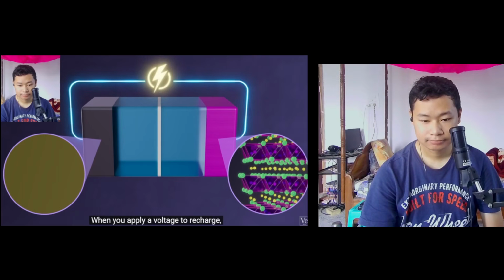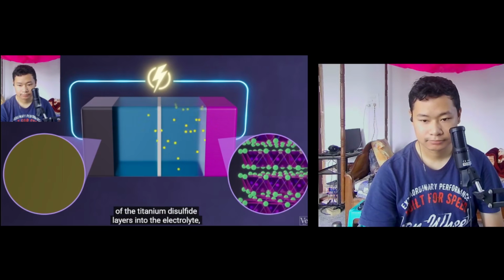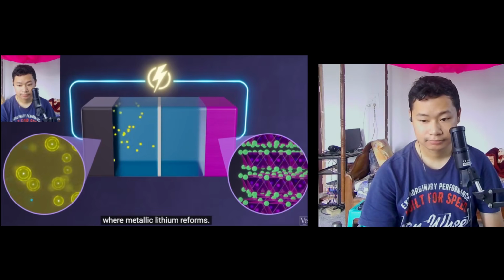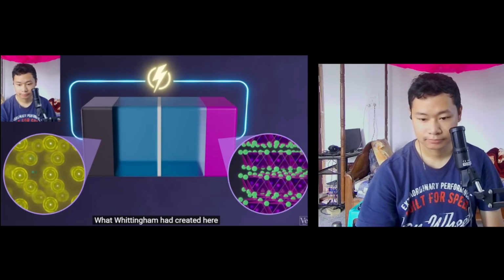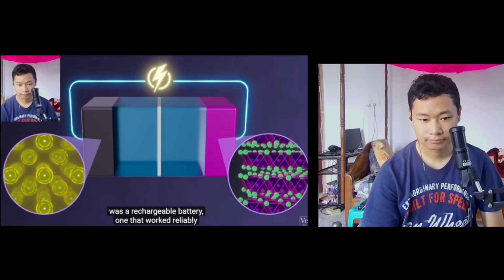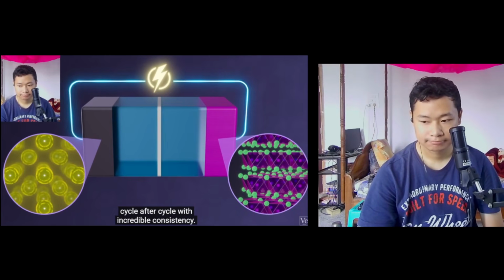When you apply voltage to recharge, the extra electrons are stripped from the titanium and pulled back to the anode. The lithium ions are forced out of the titanium disulfide layers into the electrolyte, and they too migrate to the anode where metallic lithium reforms. What Whittingham had created here was a rechargeable battery, one that worked reliably, cycle after cycle with incredible consistency.